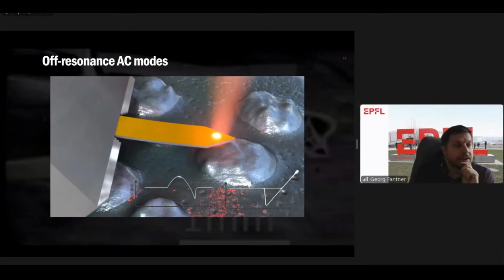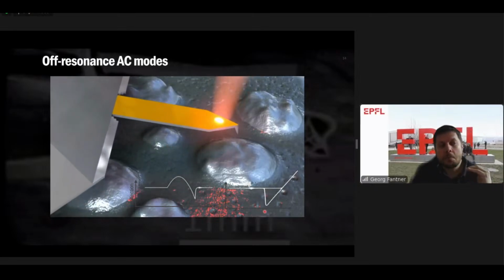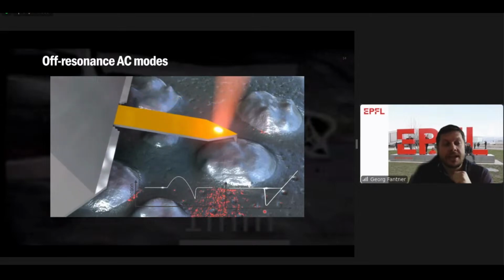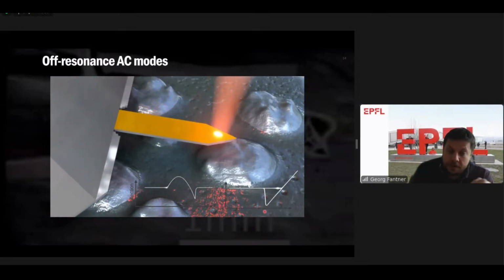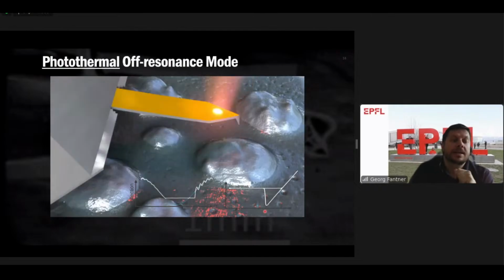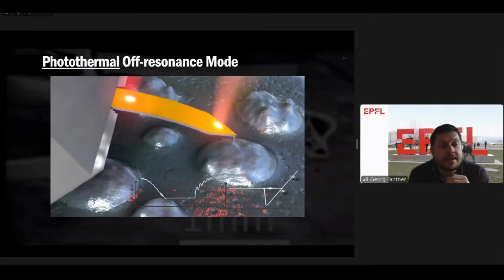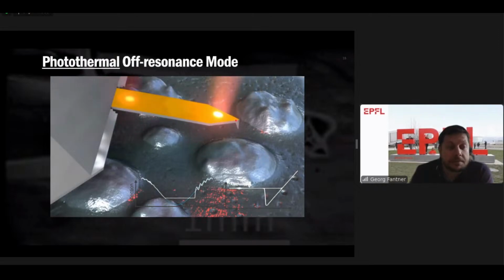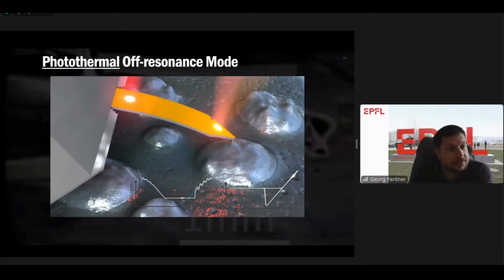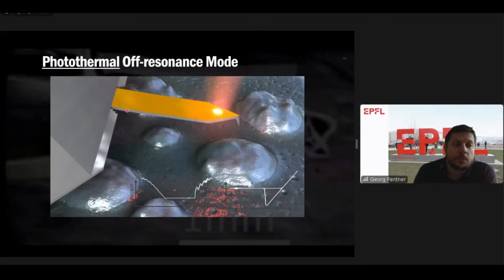So what we've done now is we've said, okay, all we need to do is modulate the tip-sample interaction. And instead of doing that by going up and down mechanically with the piezo, what we did is we added a second laser beam into our microscope. And that second laser beam is focused at the base of the cantilever. The first laser beam sits at the tip of the cantilever, like in every other AFM, to read out the deflection. But the second one is focused at the base. And instead of shining a constant light on it, we pulse the light that we are putting on here.